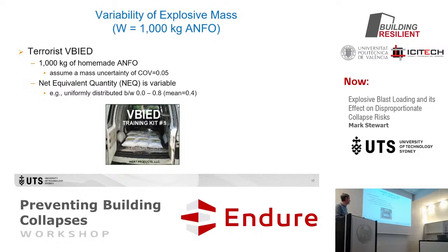Right, and there's uncertainties. So you might have 1,000 kilograms of ANFO, ammonium nitrate fuel oil, which can be homemade and mixed. Let's assume it's 1,000 kilograms. When the terrorists make it, they might aim for 1,000 kilograms, but it might actually be a bit less. It might be 950 or maybe 1,050. So there's some variability in that. We call that the coefficient of variation, which is the standard deviation divided by the mean. So that uncertainty is quite narrow.